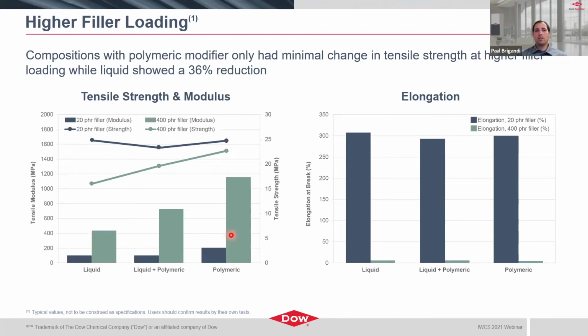But what I want to call attention to is really the tensile strength and the difference between the tensile strength in the case of the liquid versus the polymeric. So here, when we look at the 20 parts and 400 parts of filler, when you look at the polymeric, there's a very small change in the actual tensile strength of the material. So likely due to the additional homogeneity that these polymeric modifiers provide and the ability to help disperse some of these filler into the system. Whereas with the liquid, you actually see about a 36% reduction in tensile strength when you start to increase the filler load. So this tells us that we can actually utilize these materials to pack more filler into a system to achieve, let's say, higher smoke performance or smoke reduction performance, or even just maintain filler loading and get increased dispersion.